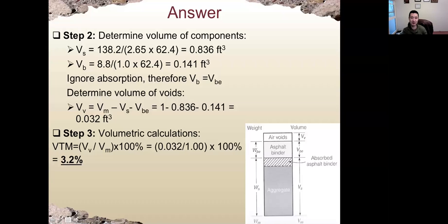Again, this is similar to the calculation we do for the mix design for Portland cement concrete. The last step is we calculate how much volume is occupied by voids by doing the subtraction. The total volume is 1 cubic foot minus the volume occupied by aggregate minus the volume occupied by binder. So the volume of voids is 0.032 cubic foot. So we can calculate VTM, the volume of voids in the total mix, and from there it is 3.2%.